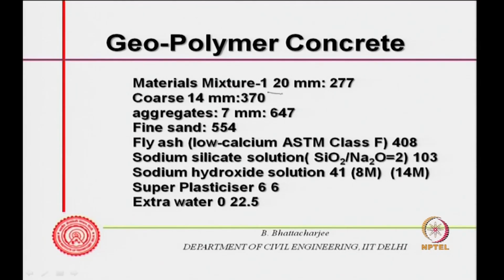A typical mixture of this geopolymer concrete would look like this: 20 mm aggregate, about 277 kg per meter cube of concrete, coarse aggregate 14 mm, this is the second coarse aggregate, 370 kg, and 7 mm, 647 kg. So, you have 277, 370, it will depend upon packing density. 647 would make it something like 1200, you know.